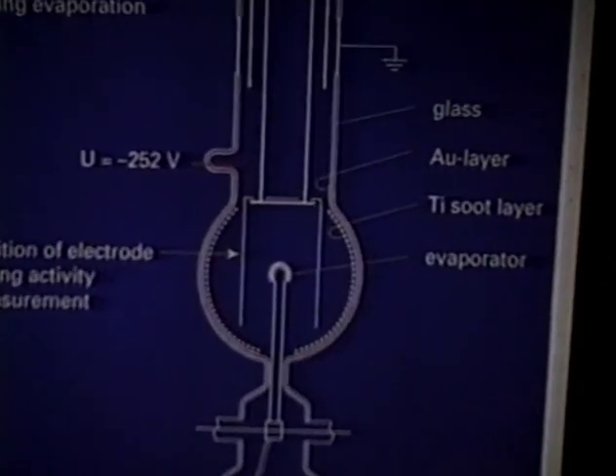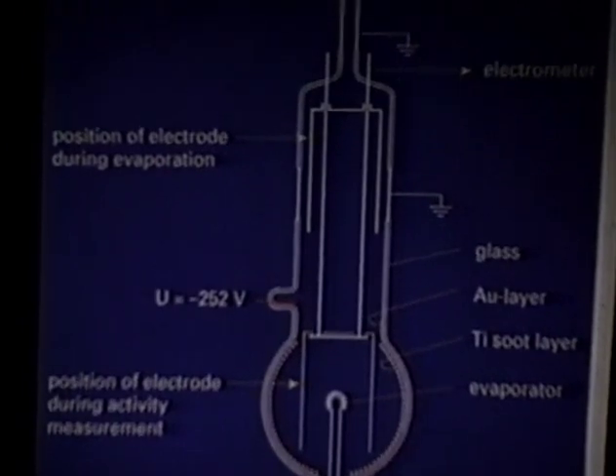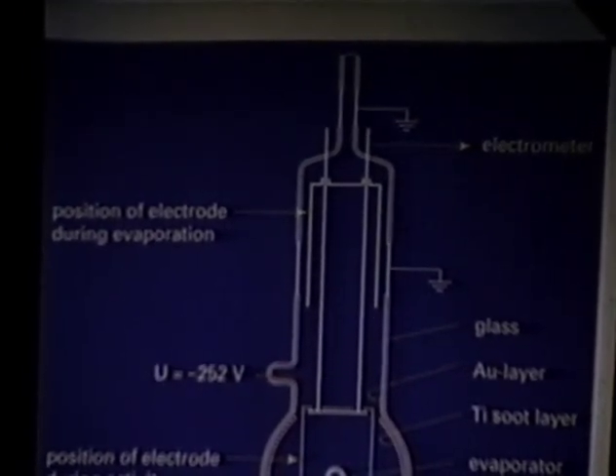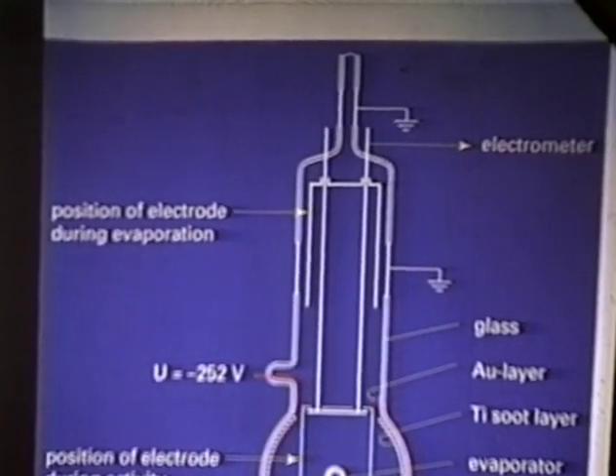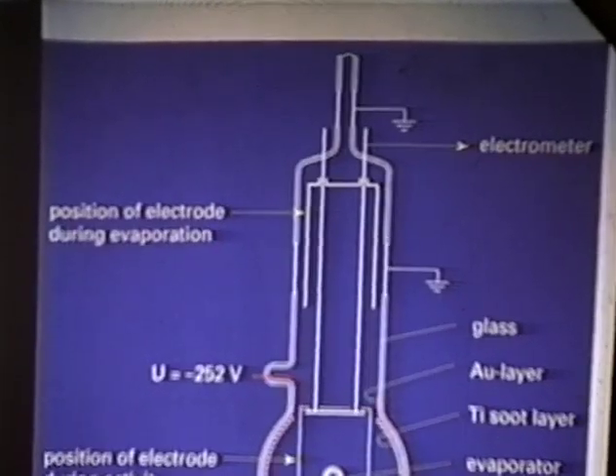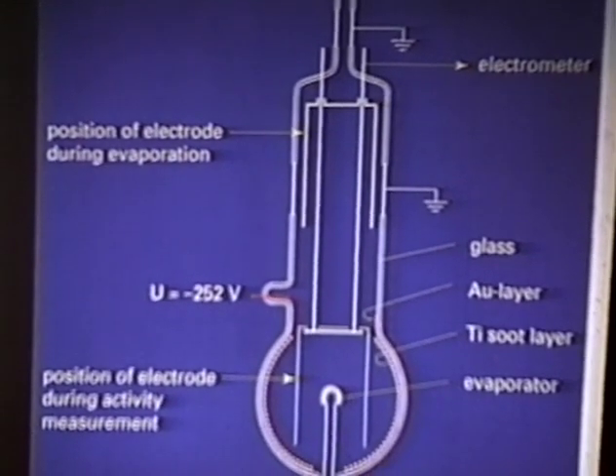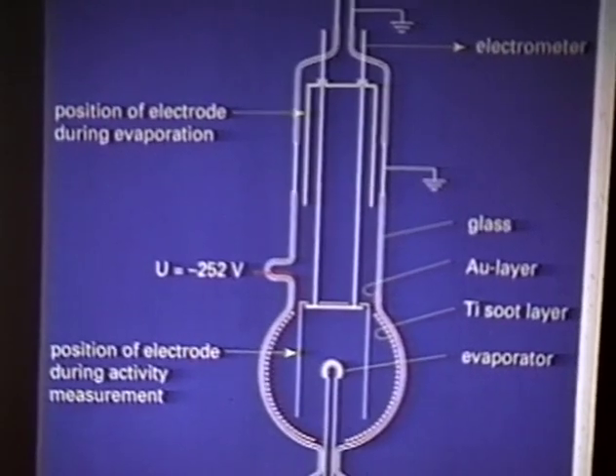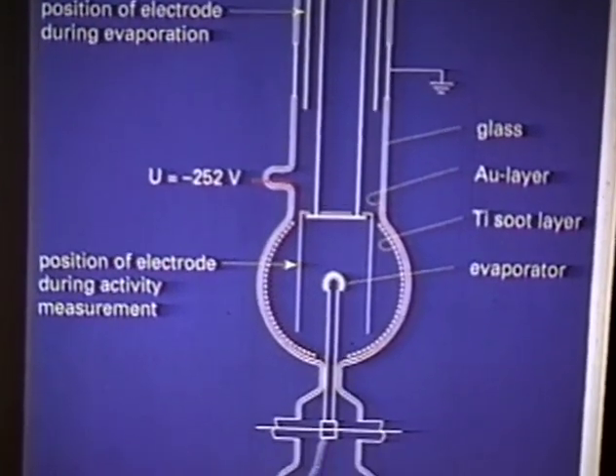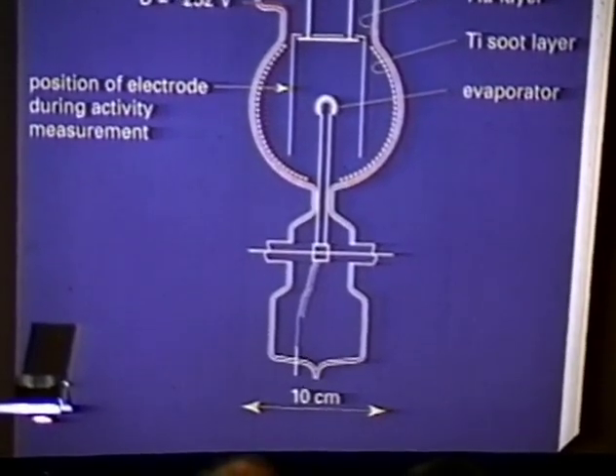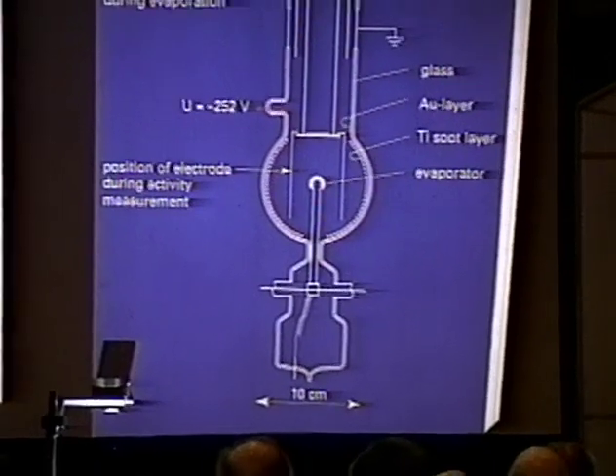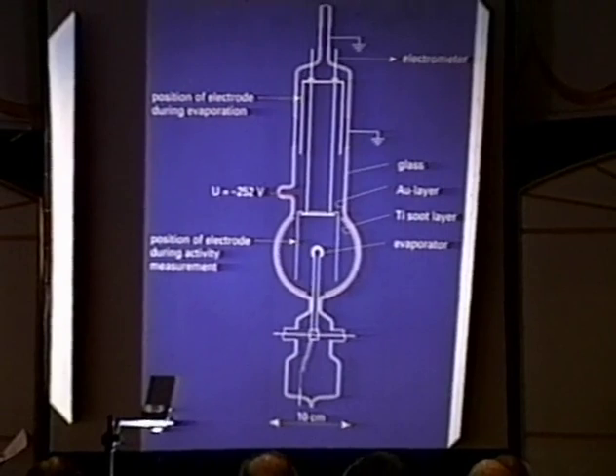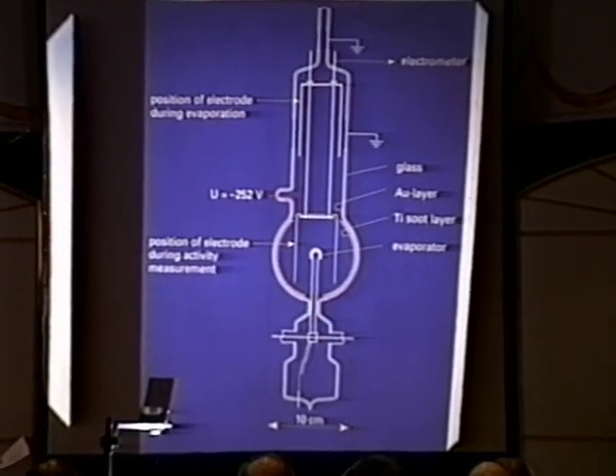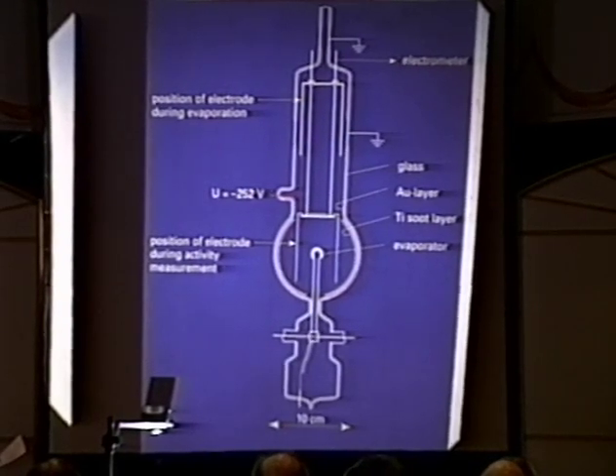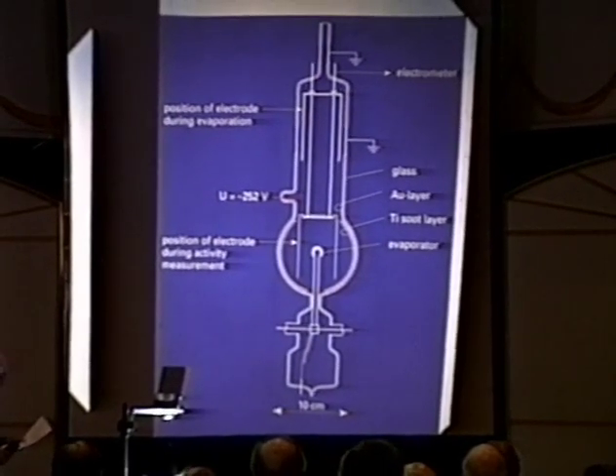By our heating experiments, we arrived at the conclusion that a new compound of the tritium with a decreased radioactive decay constant is formed in our preparations. However, there is no physical effect known which accomplishes the observed decrease of radioactivity. We have speculated that the decrease of the radioactivity may have something to do with the different phases in the titanium tritium system, a suspicion which has not been confirmed till now. Therefore, experiments were undertaken to measure the radioactivity as a function of the concentration of such systems. The concentration was taken as independent variable X, and the relating experiments are therefore indicated as TiTX experiments.